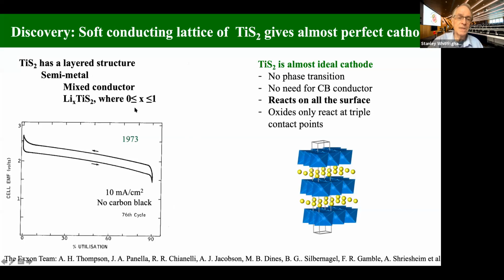It also is single phase. So it has exactly the same structure with no lithium in it and up to 1 lithium. So no energy is expended in nucleating a new phase. And I show you a typical discharge curve. It starts out about 2.3 volts, ends up about 1.8 volts. And the slow decline in the voltage is due to the conduction band being filled with the electrons. So you get less and less energy out of it.